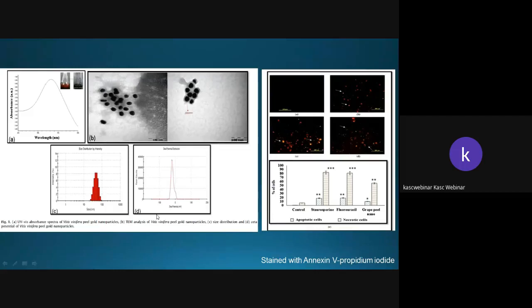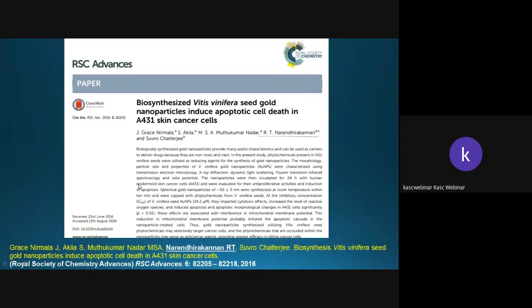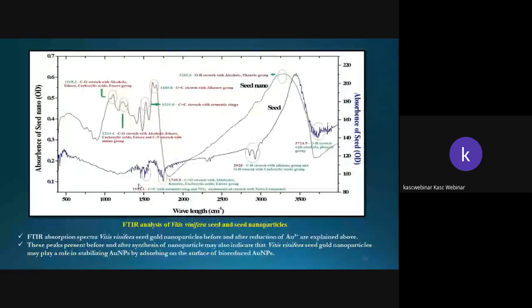So we have studied the stability and size, diameter, through this paper. And another one we have just checked is in RSC Advances. Here we have the FTIR analysis, which shows the spectra of the grape seed extract and the synthesized nanoparticles compared, to analyze the changes in the peaks before and after bioreduction. Here you can see the FTIR spectrum.